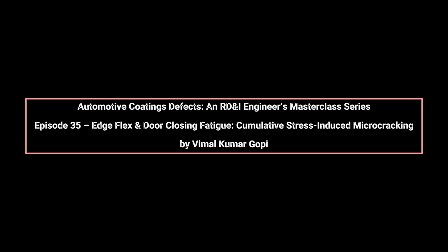Spray patterns deposit less material on sharp radii, and surface tension pulls liquid coatings away from corners during flow and bake. As a result, coatings at edges operate closer to their mechanical limits from day one. When flexing occurs, these thin regions experience higher strain per cycle than flat panels. Microcracking is the earliest manifestation of fatigue failure.